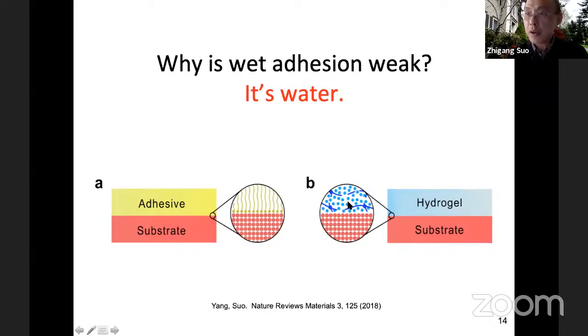Still a lot. But if you have a hydrogel, we said hydrogel is 90% water. So 90% water flows. Even the first layer of water, let's say, bonds very well with the substrate—okay, 100% bonding. But your second layer of water still flows relative to the first layer of water. So you can never win. Your adhesion energy essentially is limited by the adhesion between water molecules in the liquid state. It's not much, right? So that's why you're doomed.